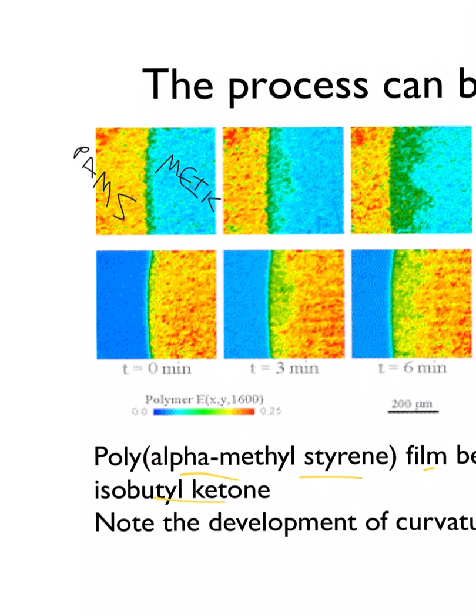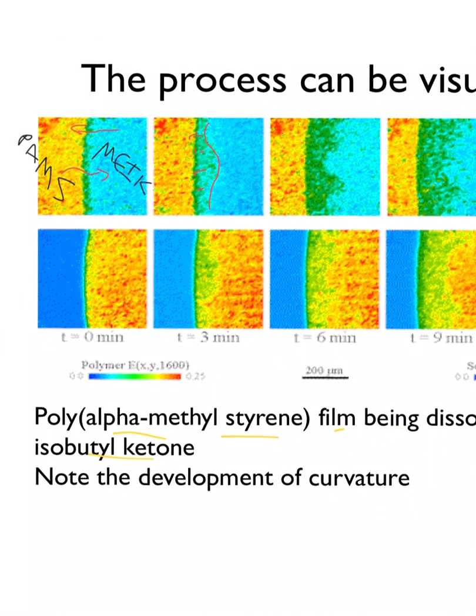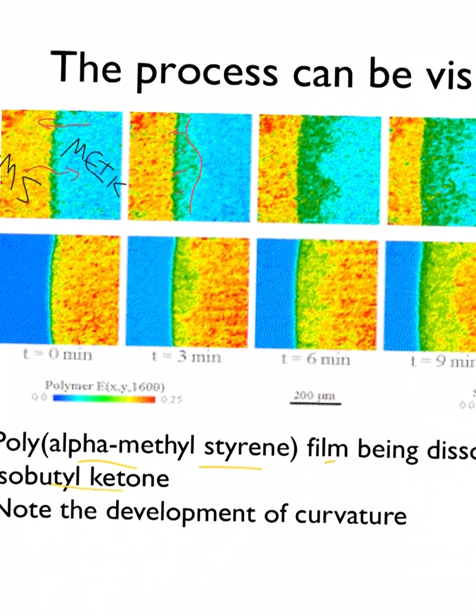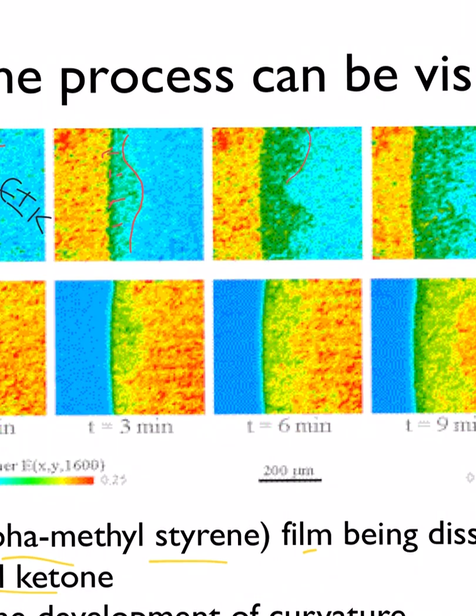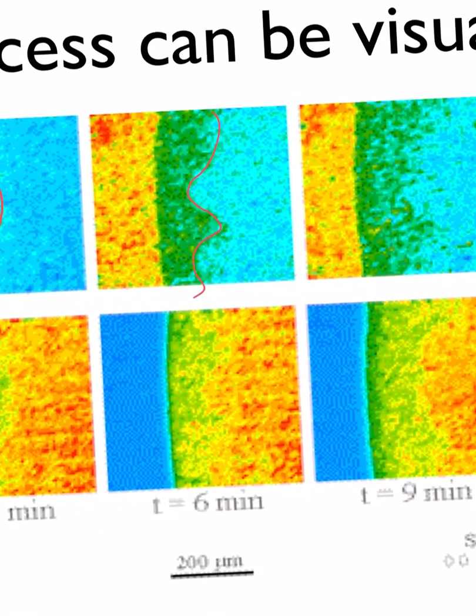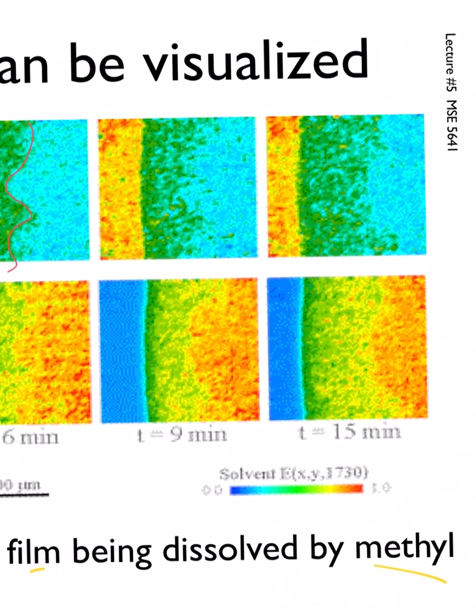And so what's happening is these guys are seeing each other across that interface, and as you already know, the solvent's going to try to go into the polymer, and the polymer is going to try to go into the solvent. And so what you start seeing here is this interface forming in which some of the polymer chains are starting to extend in that solvent. That's where the green color is coming from. And you're also getting solvent going into the polymer, which is where the darker green color is coming from. And then as time goes by, this is 0 minutes, 3 minutes, 6 minutes, 9 minutes. At 6 minutes, that interfacial phase is a fairly large fraction of what we're looking at. And then at 9 minutes, 15 minutes, it's grown even more.